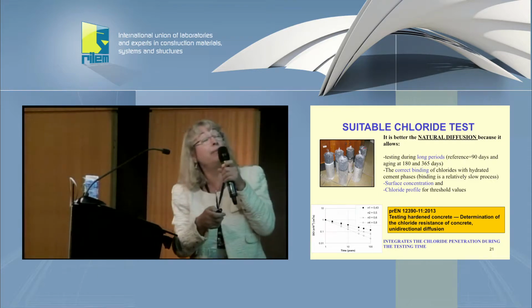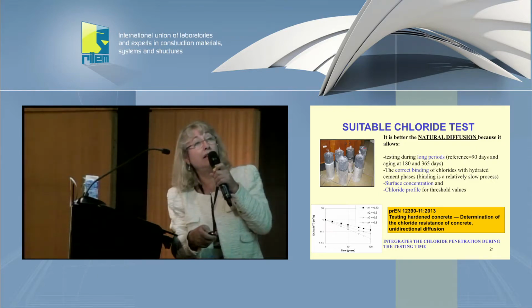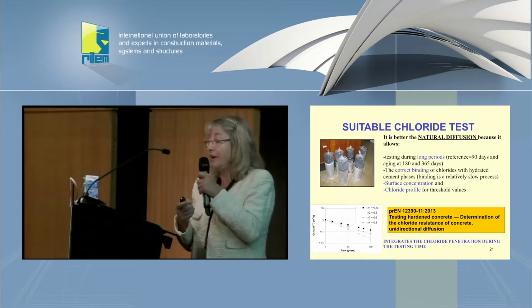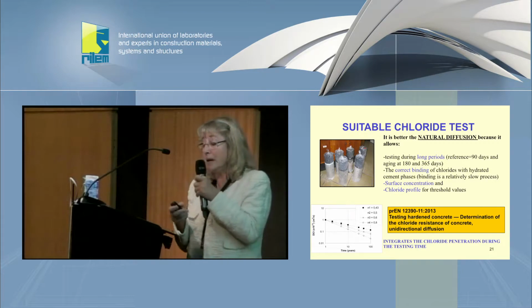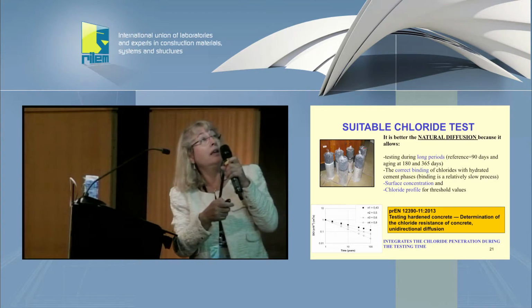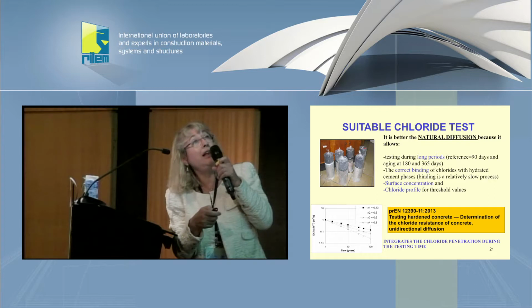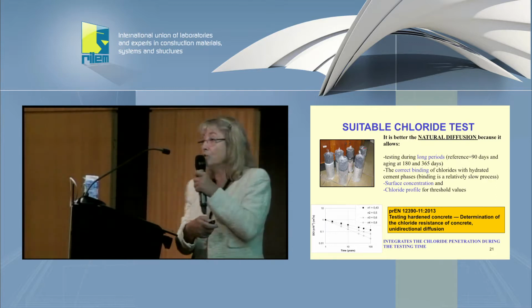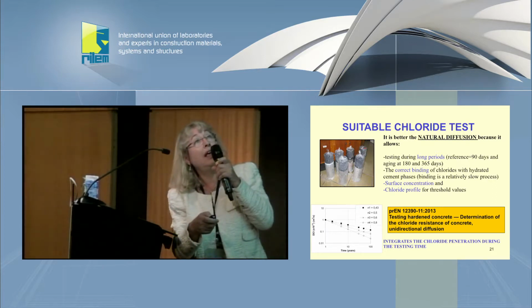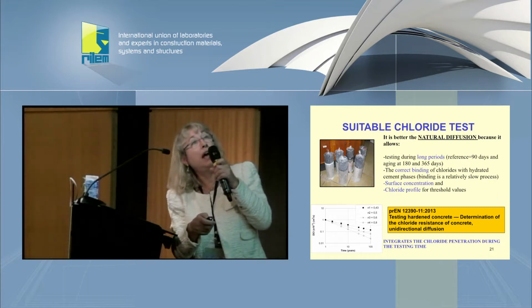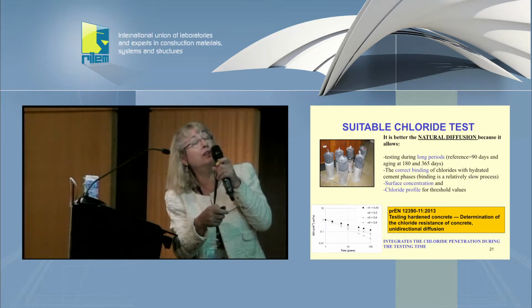I find very many advantages, and in fact at European level this is the test that has been standardized as reference. As I will say, you can use others but not as reference. Why? It's the best we have, mainly because it's able to keep salt water in contact with the concrete continuously. Because if we need to study aging, we need maybe even 1 year long periods of contact, and it's necessary to have the salt water in contact permanently.